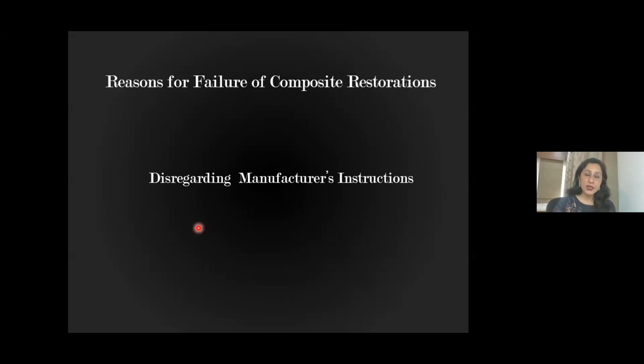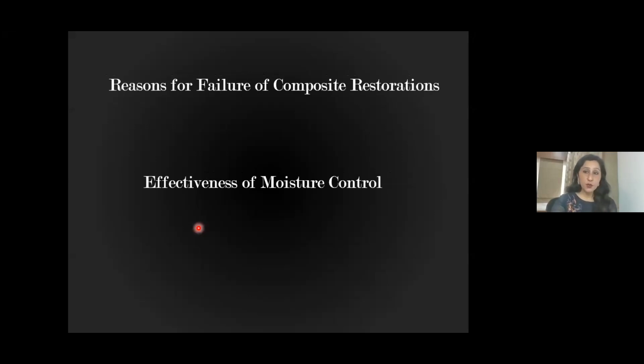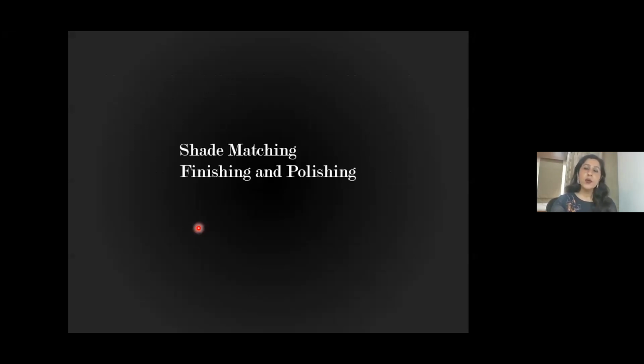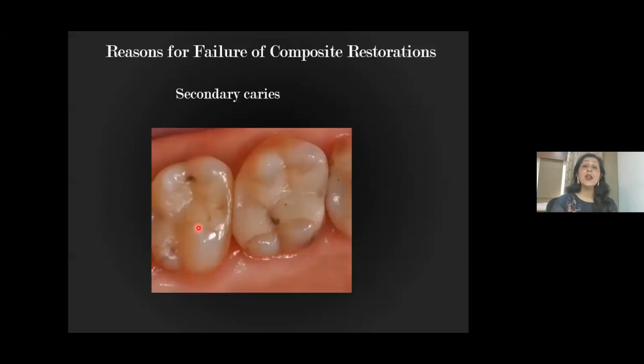So a reason for failure of composite restorations is disregarding the manufacturer's instructions. If you don't follow the manufacturer's instructions, we've talked about this in detail. Another reason is ineffective moisture control, when you do not use a rubber dam, or when you do not isolate well. The main thing is that whichever way you are well adapted with isolation, you should do that. Shade matching, finishing and polishing should be done in the proper fashion. Otherwise, again, you will lose your restorations very early.